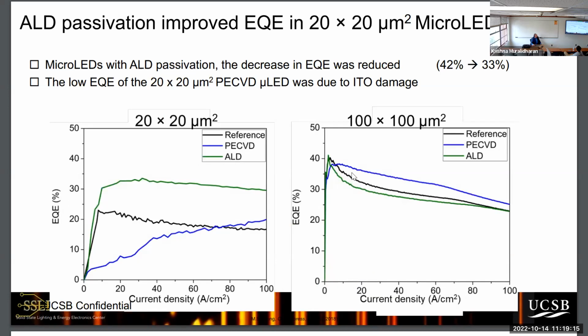And this shows you again, so this was a 100 micron device. This was its efficiency versus current. It's not too affected by the sidewalls, but the small devices completely affected. The blue would have been the standard process, but you can see the atomic layer deposition is here. So that means we have now 33% efficiency, which is much, much better than an LCD screen. This current TV you're looking at is 3% efficient. So we're already 10 times more efficient than this TV screen.